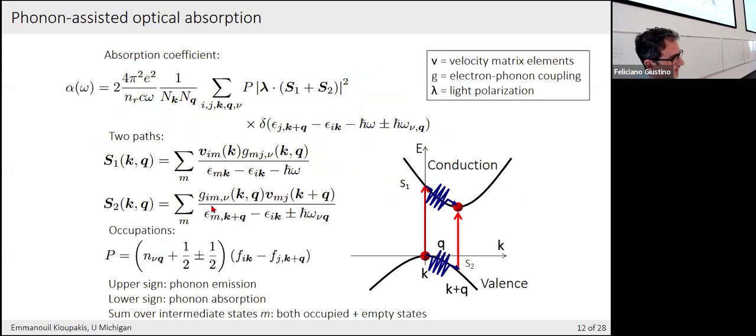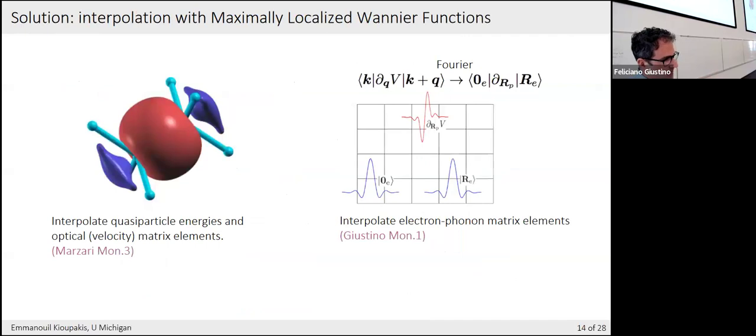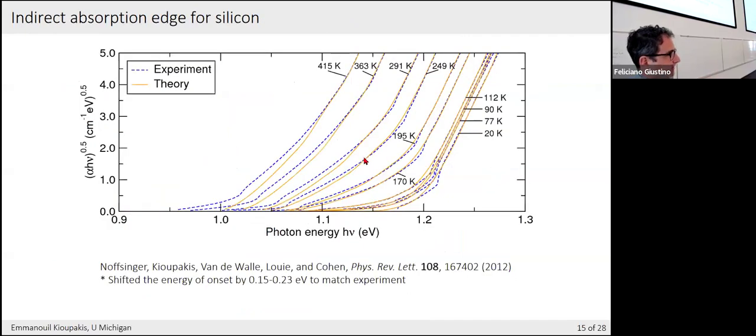But another more important factor is the eigenvalues. The bandgap depends on temperature in general. And so phonons renormalize the bandgap, the eigenvalues, as we saw in lectures about the ARPES spectra that show these kinks once you put in phonons. So that is the biggest contribution that is missing from our calculation here. At the time when we did this work, the theories were not developed, the codes were not ready yet.